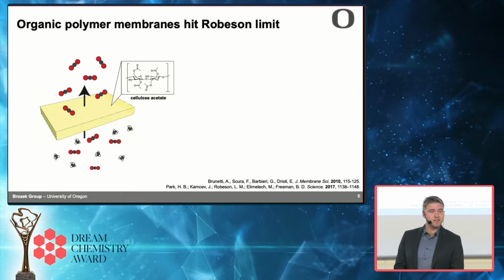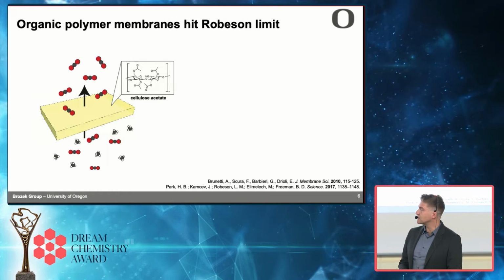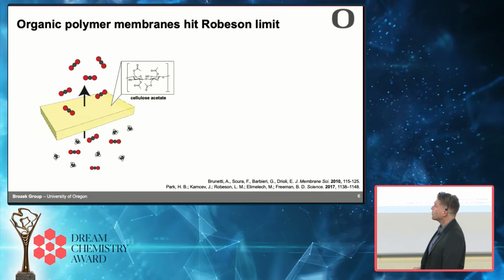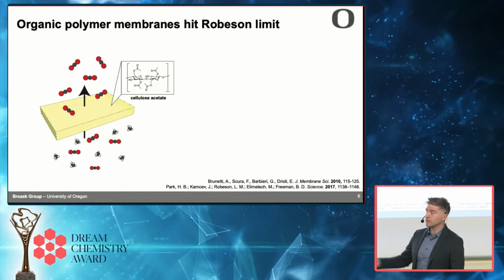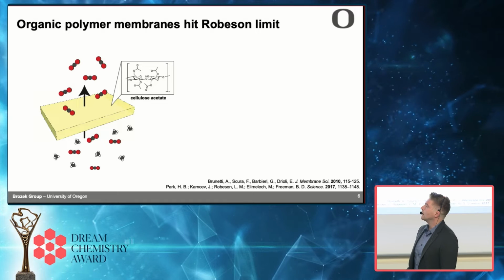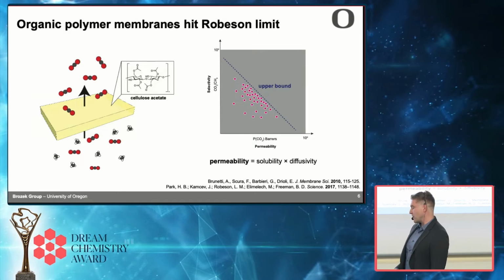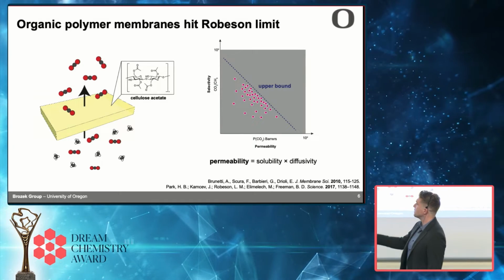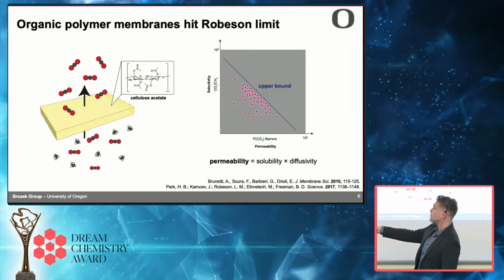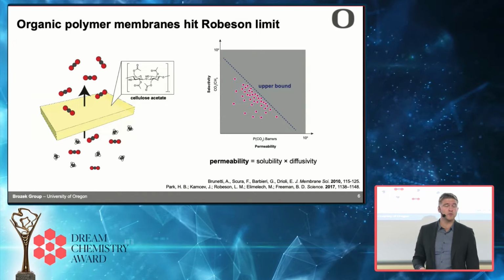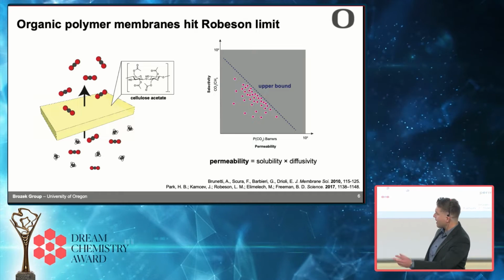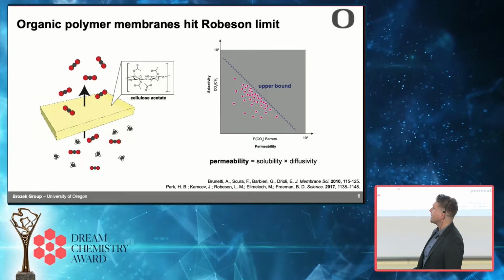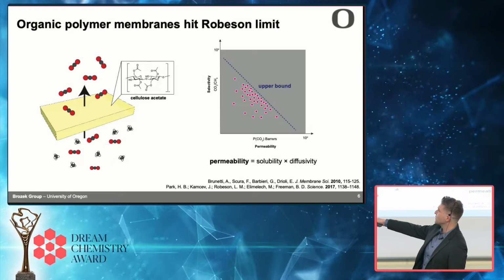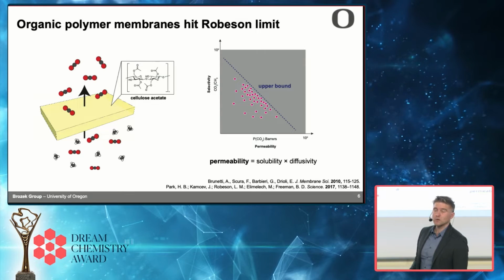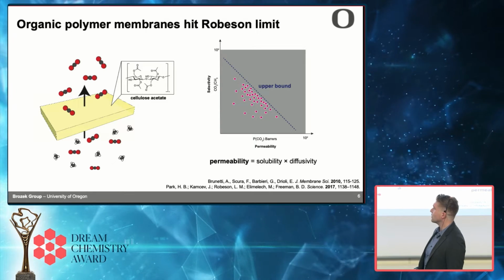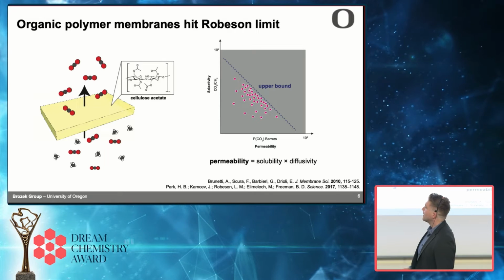And cellulose acetate is nice because it's readily abundant, relatively inexpensive. So you can use something like cellulose acetate to separate, in this example, methane from CO2. And you can evaluate the performance of these membranes. When you do this, you can plot how selective your membrane is versus how permeable your membrane is. And people have accumulated enough data to see that as you evaluate more and more membranes, you hit this so-called upper bound.